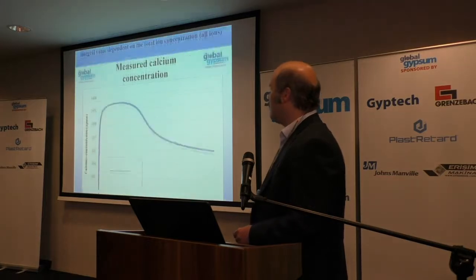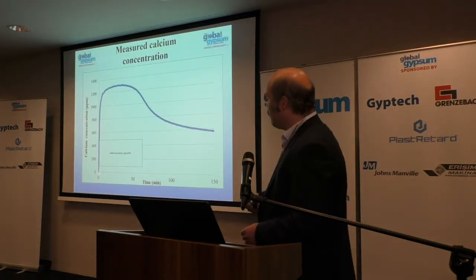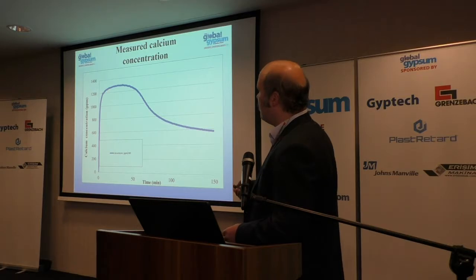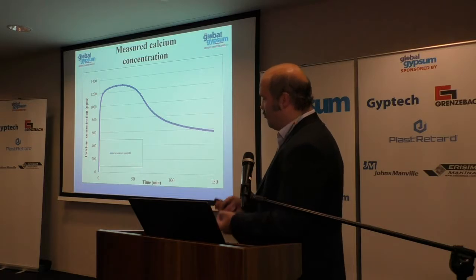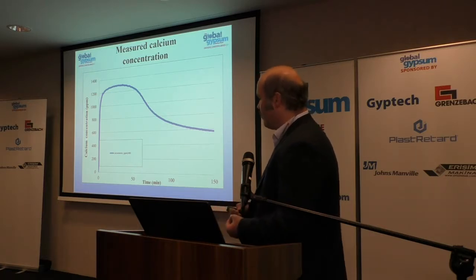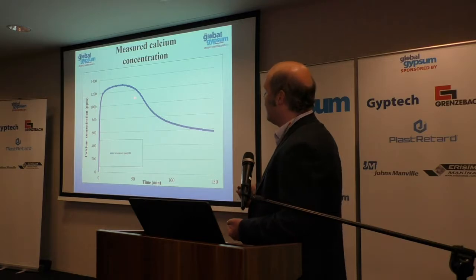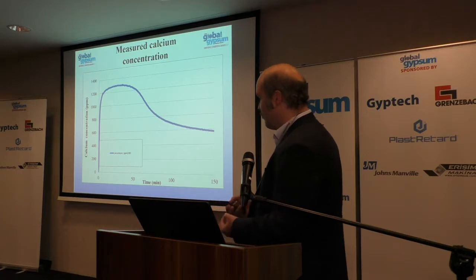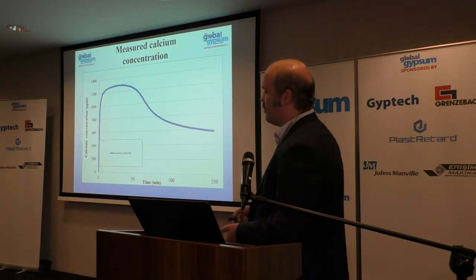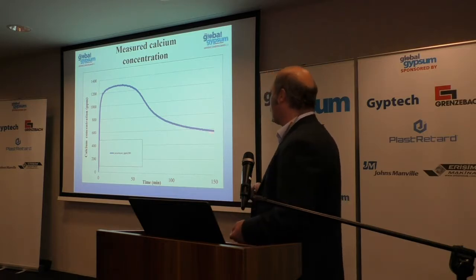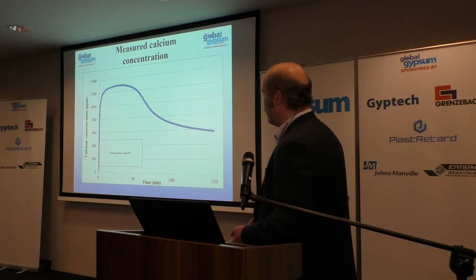So let's check how such a result looks like. Here we have the increase of concentration of calcium in the solution because of the dissolving of hemihydrate. And you have the creation of seed crystals, and they start to grow. And in this part, you have as much hemihydrate dissolved as you need for the growing of the gypsum crystal. It's more or less in equilibrium. And now most of the hemihydrate is dissolved, and I cannot deliver as many ions as I need for the crystallization of dihydrate. So the concentration gets lower and lower until hemihydrate is nearly completely gone. And it will stop around the solubility of dihydrate. You will not reach zero.